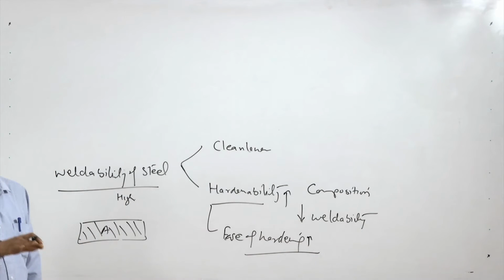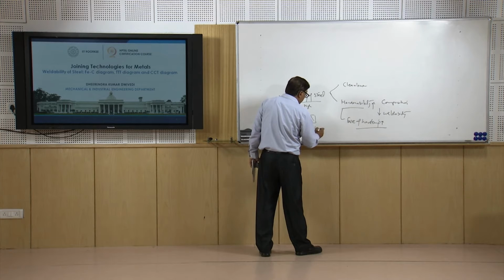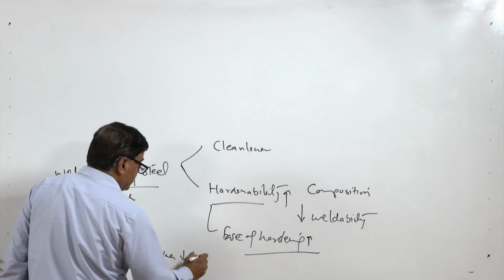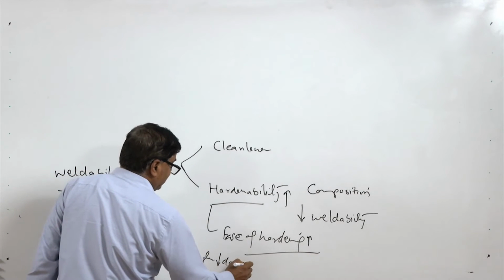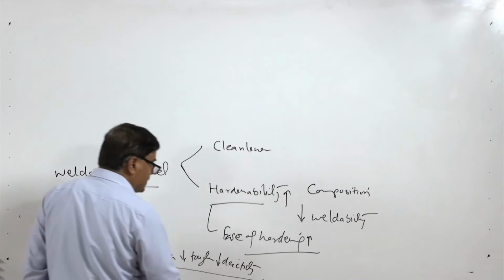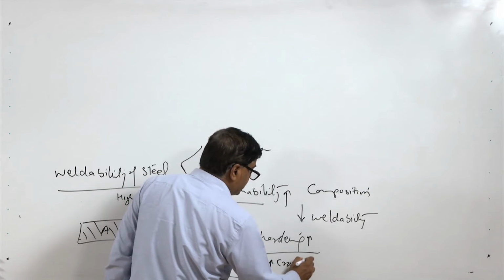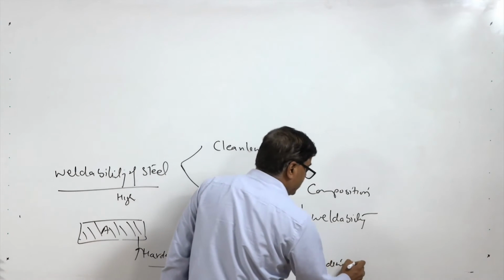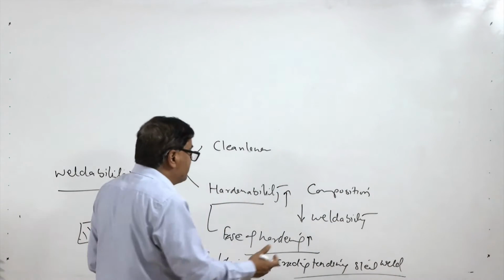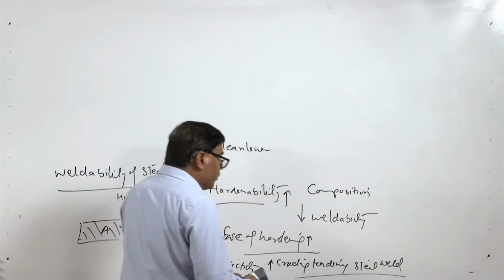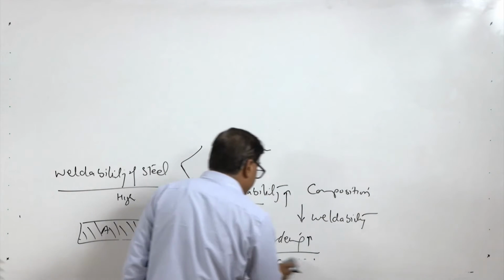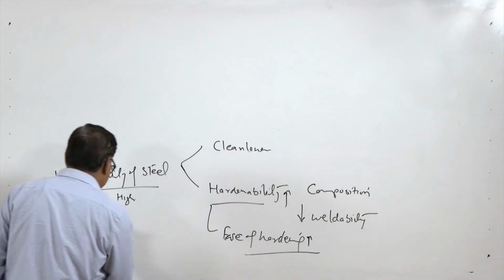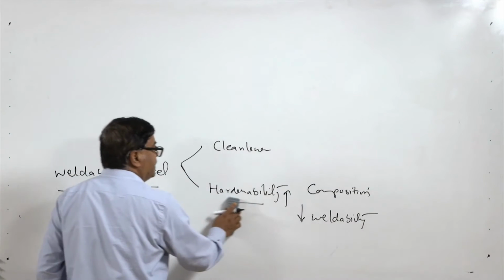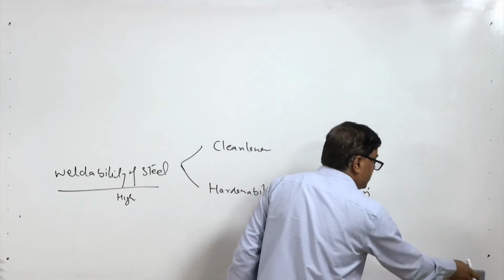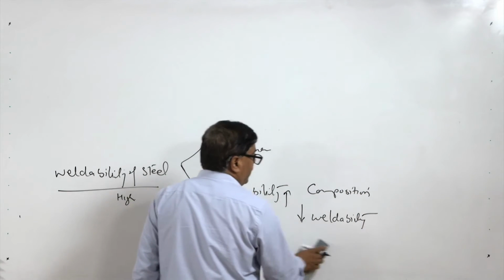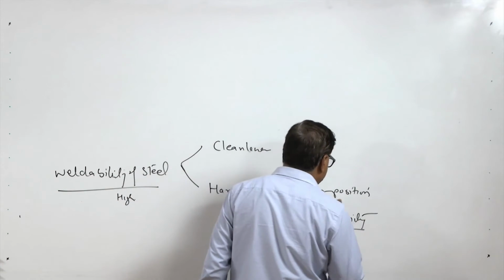easily, through the transformation of austenite into martensite, and this will result in high hardness, reduced toughness, reduced ductility, and increased hardness. All these properties actually increase the cracking tendency of the steel welds. And if the weld is made with cracks, then it is of no use. So, it requires more preheat. More effort is required for preheating. It will be more difficult to weld the preheated base plate as compared to a plate at normal ambient conditions, and that is why, as the hardenability increases, the cracking tendency of the weld also increases. Therefore, we require more care to avoid cracking of the weld, which in turn reduces the ease of welding, or the weldability.